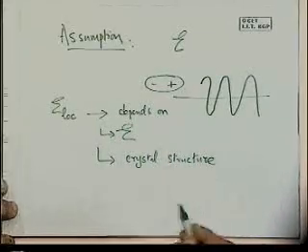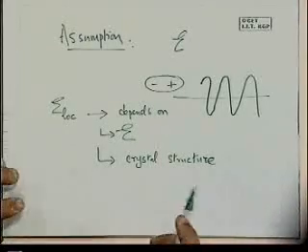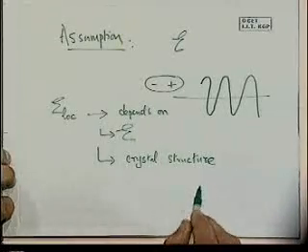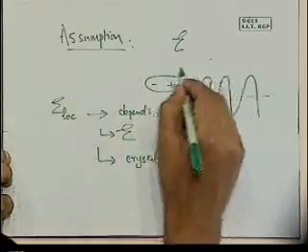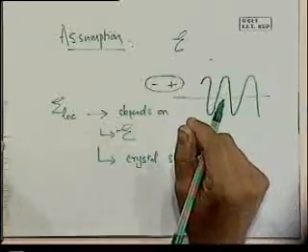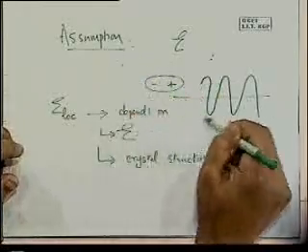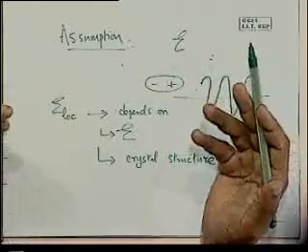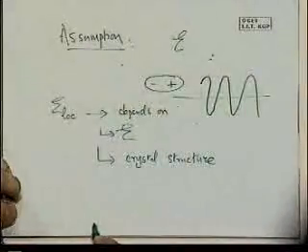And the larger is E, the larger is the average dipole moment. It will depend on the crystal structure in that all these dipoles that are around it are arranged as part of some crystalline structure, if we are considering a crystal, or if it's a gas, then we don't have to worry about it. So in that process, the exact influence of these other dipoles that are around this particular dipole that we are concerned about will depend on the crystal structure. And to that extent, we have to worry about what is the crystal structure.